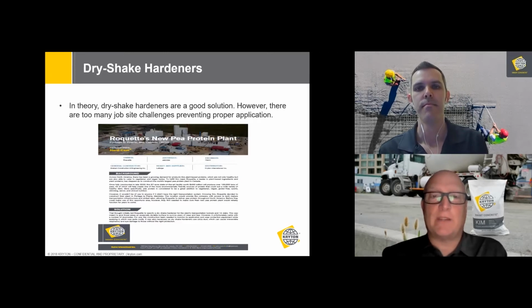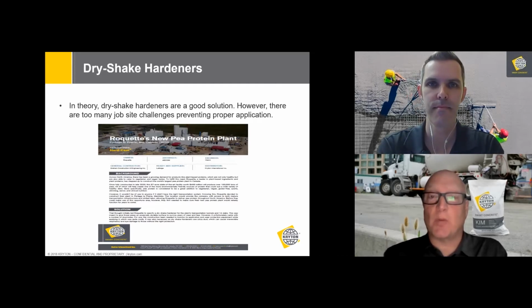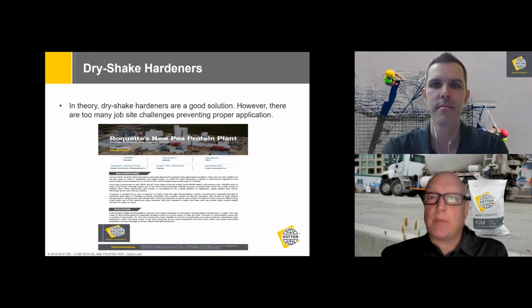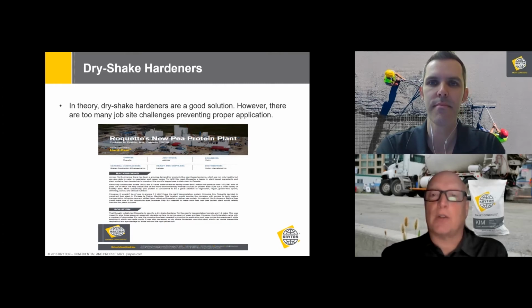Jeff, you've just described the conditions that Graham Construction experienced while building North America's largest pea protein plant in Manitoba. They have large slab pours, and during the first slab, with the specified shake-on hardener, they had a challenge of getting that down in that very finite window of opportunity. And they ended up losing the first slab. Graham then approached the engineer of record and suggested that Hard-Cem be used. The engineer did their diligence and approved Hard-Cem for the balance of the project. And they did end up having to remove that first slab and replace it. So exactly the conditions you explained, the end of the day, trying to get down that shake-on, and they eliminated that by adding Hard-Cem into the back of the concrete truck at the batch plant.